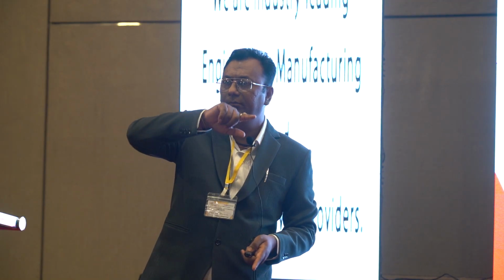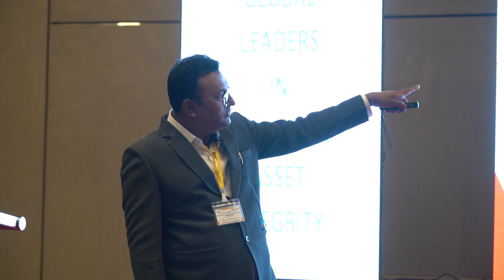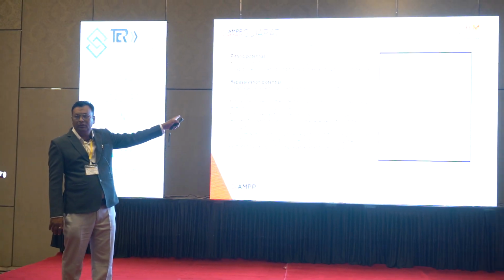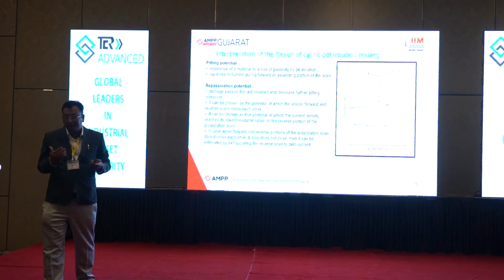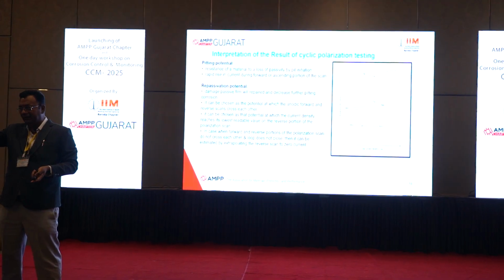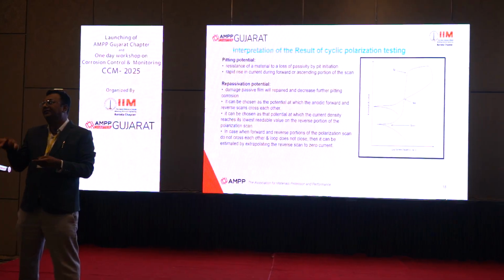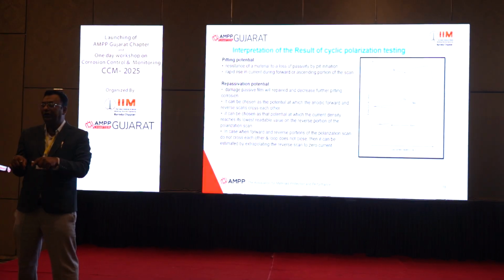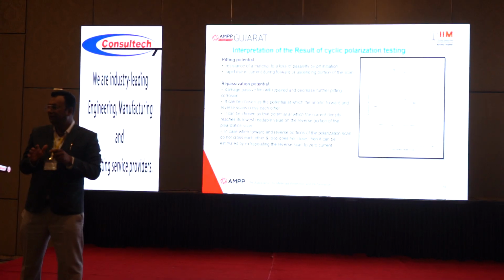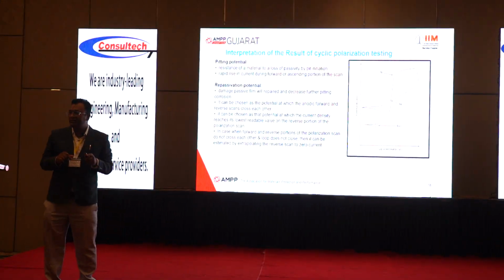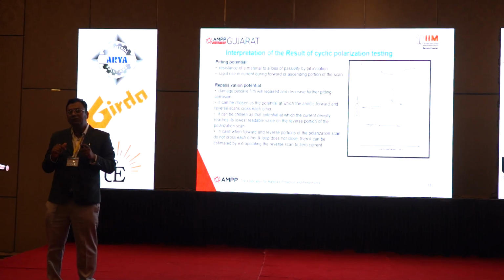Now, how to analyze the data? Whenever a loop is formed, it will intersect and cut itself at a certain location. That location is called the repassivation potential. In the potentiodynamic forward scan, it reaches a certain value and pits start to form. That is the value where pits start. But we want to understand how the pit gets repaired during service conditions, and whether this alloy can reduce the pitting behavior. So we look at whether it intercepts at the point called repassivation potential, which is very important.